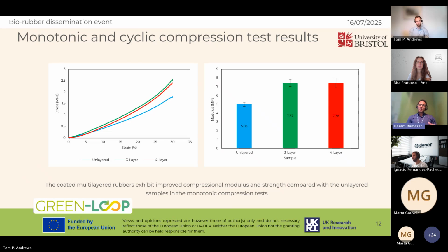To evaluate the performance of these rubbers, we performed a series of tests, and you can see the results of the monotonic and cyclic compression tests. So here we have the monotonic compression test, and as you can see from the stress-strain plot, the multi-layered rubber have a better performance in terms of compressional strength compared to the unlayered sample, and also a higher modulus.